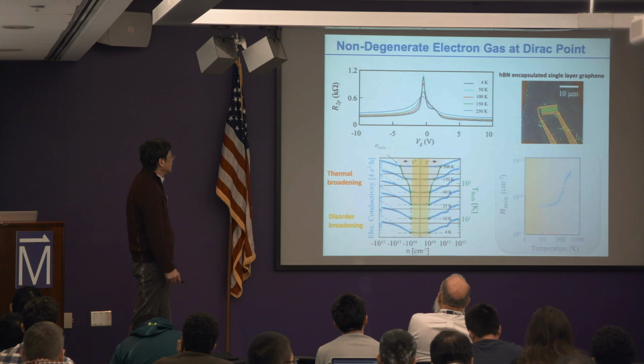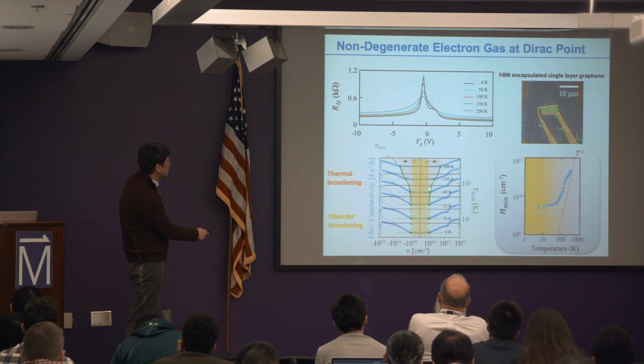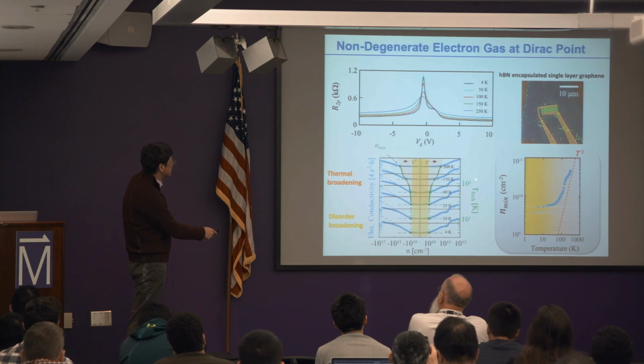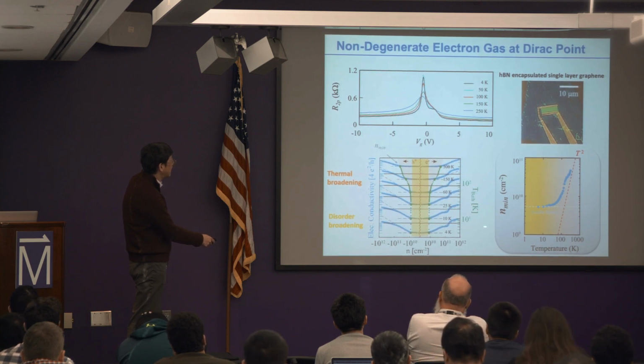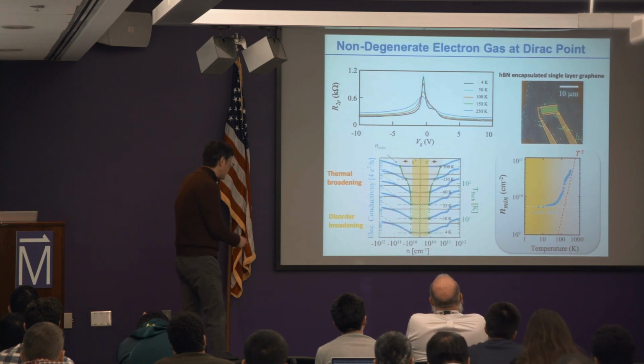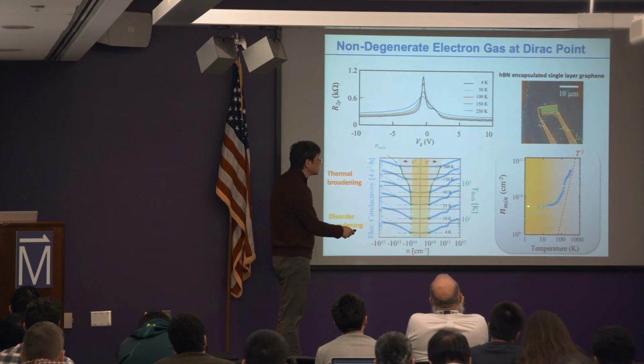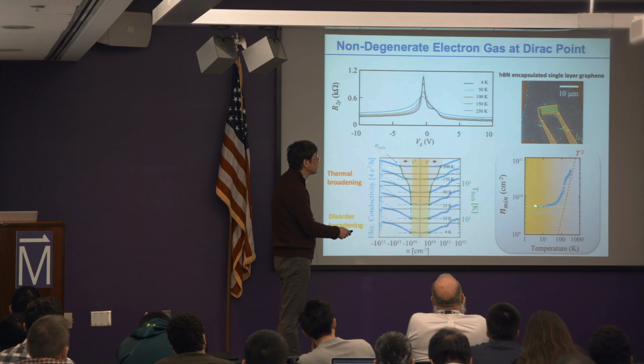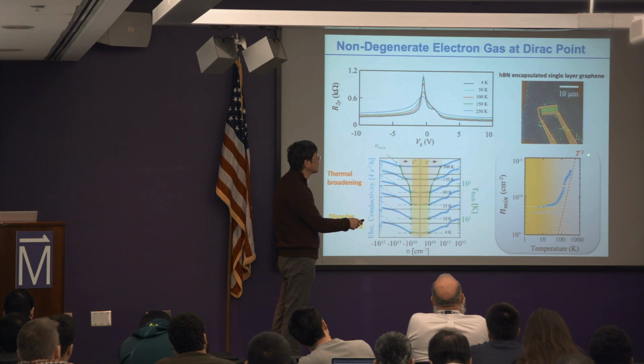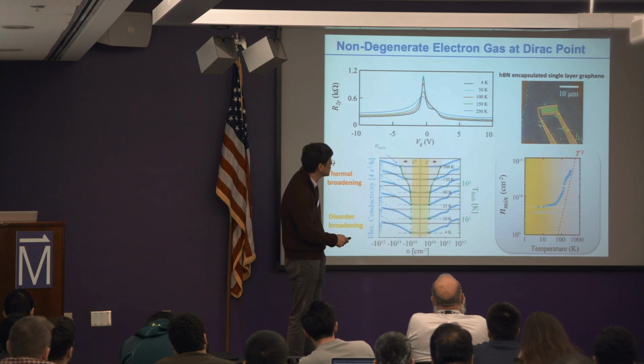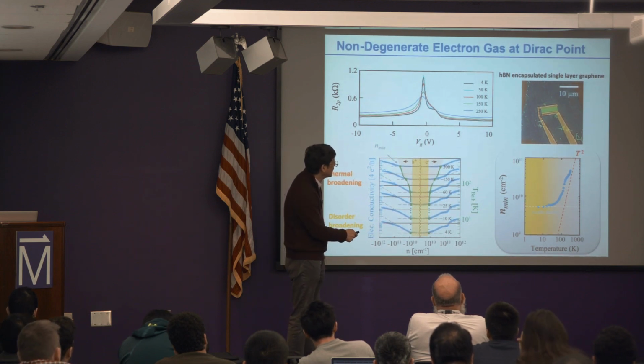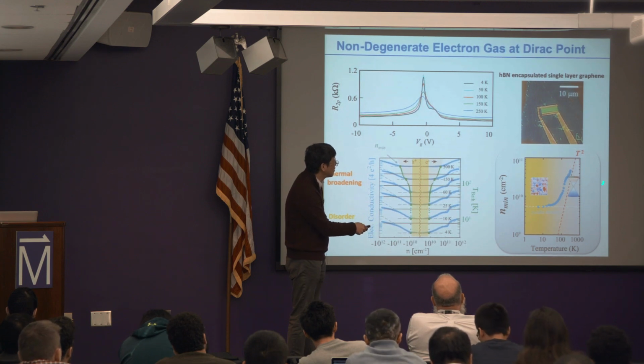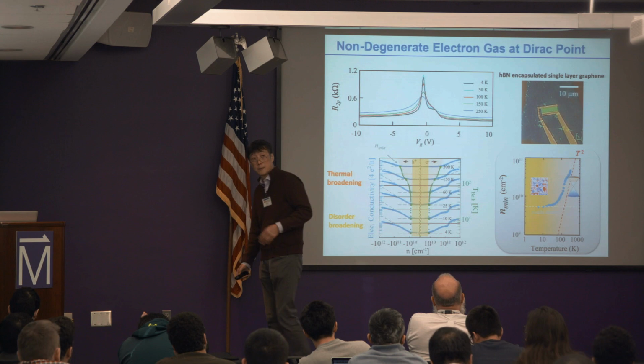Okay. So if I just plot out this inflection point, in other words, where that constant increases, and then I track that, I will call that my minimum density, which is related to about half max of the full width of this peak. That's more like the indication of what the temperature effect looks like. So again, the minimum point is more or less constant at low temperature and starts to increase, and the increase roughly follows T-squared, which is actually expected from thermal population. So that tells us that I have the disorder dominated regime turning into more thermally populated electron hole systems experimentally, right?